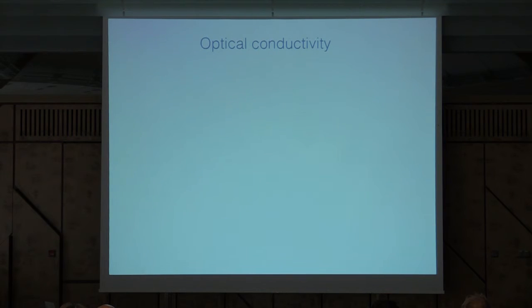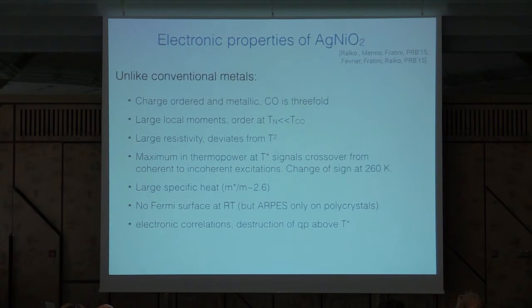And then optical conductivity, we know that this is the smoking gun. We learn a lot from here. Nobody has measured it. So Martin, you know what you have to do. I think it would be really interesting to measure this and transfers of spectral weight. OK, to summarize the experiments, this material has charge ordering. The charge ordering is threefold. There are large local moments pointing to these localized spins.